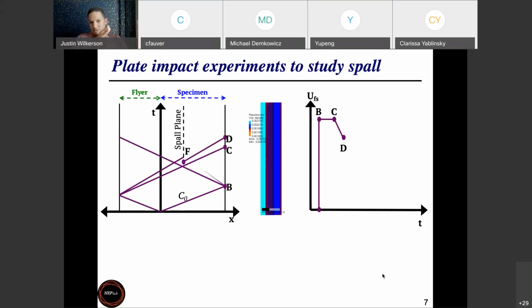So you can see as a wave comes by, it first needs to take you from 0 stress to, let's say, 1 GPa, and then 2 GPa, and then 3 GPa, and then 4 GPa. Those at higher compressive stresses have higher bulk modulus, so they have higher wave speed. So the stuff that's behind tends to move faster, and so it will catch up to the front. And that's what makes a very sharp shock wave. And this is true for both fluids and solids. It doesn't matter. It's the same for fluids and solids.